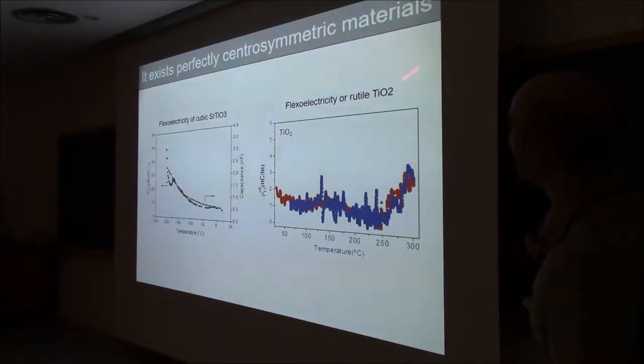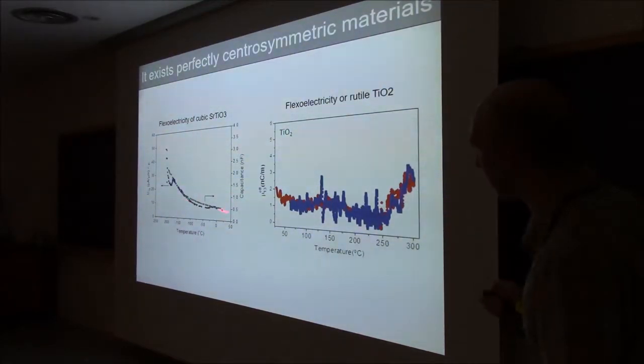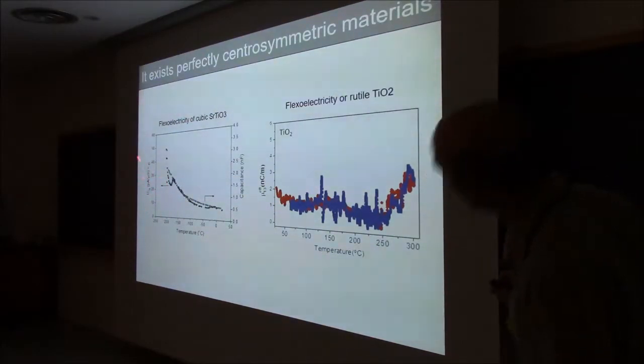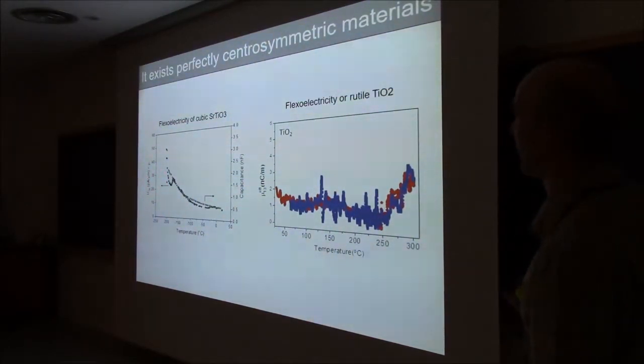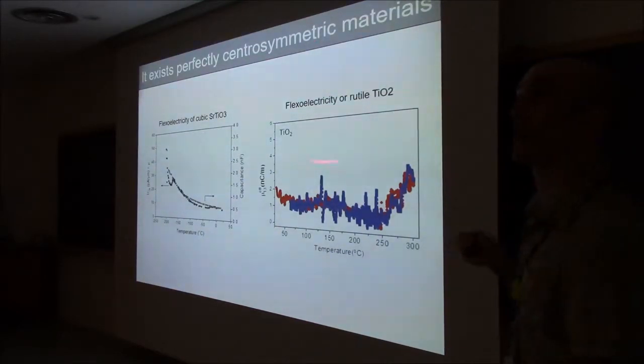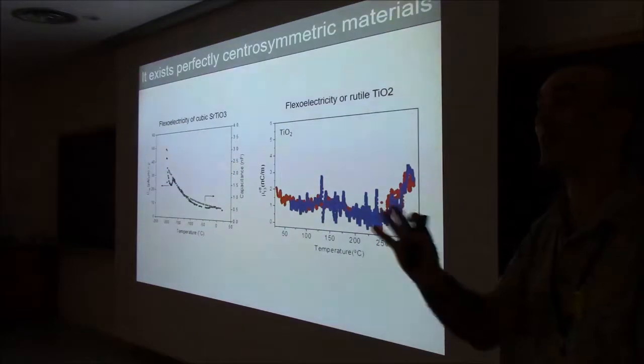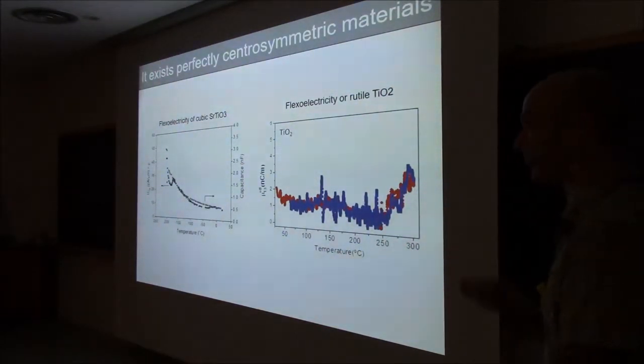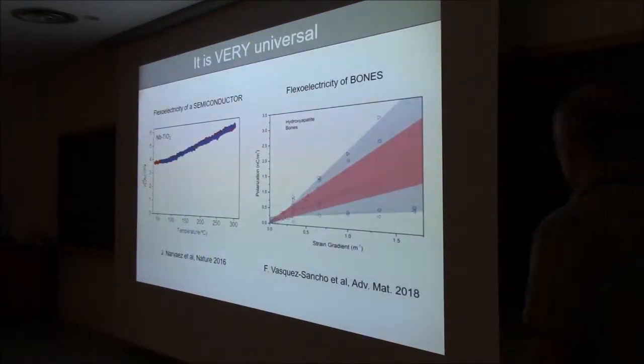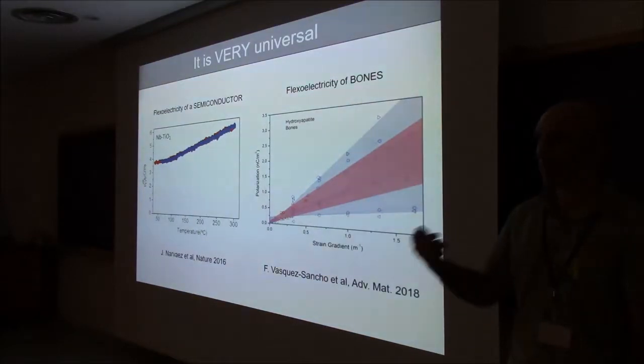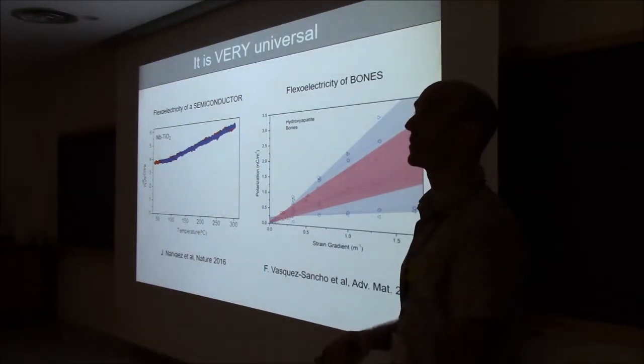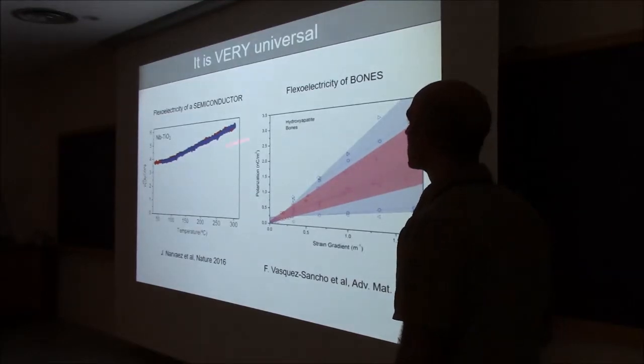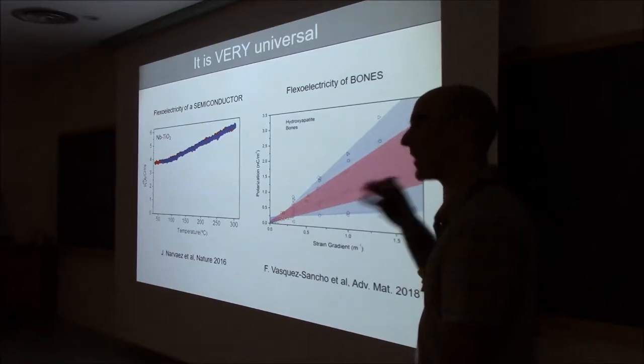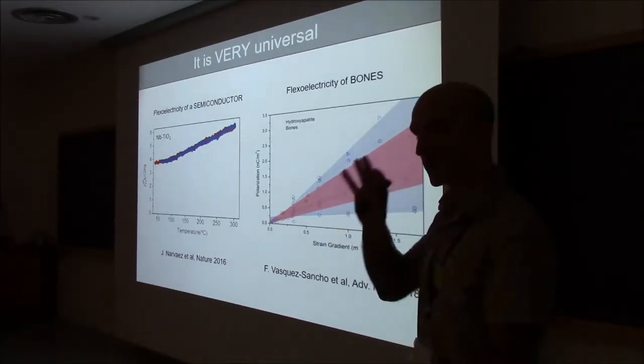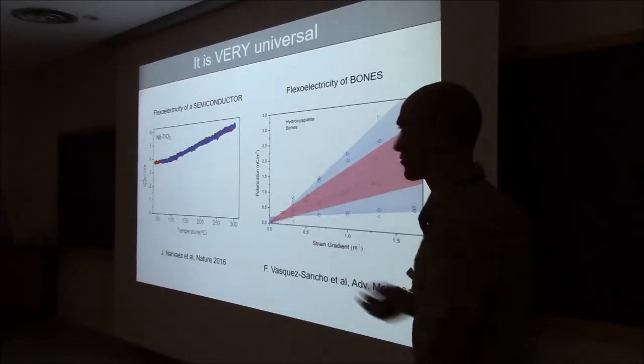Just to emphasize it, it does exist even in materials that are not ferroelectric, so you can take STO and bend it, and if you look at the flexoelectric current, this is the displacement current as a function of bending, you see that it exists, point one, and point two, that it is proportional to the capacitance, i.e. to the dielectric constant. And you can do the same, have done the same, with rutile titanium dioxide. So hopefully I convinced you that it does exist in centrosymmetric materials. It's a properly universal effect. In fact, it's even more universal than you might think, because it doesn't just exist in all dielectrics, more or less irrespective of symmetry, but it also exists in semiconductors. And I will explain later why you can get flexoelectricity in a semiconductor, because it's not trivial, it's not exactly the same as standard flexoelectricity.